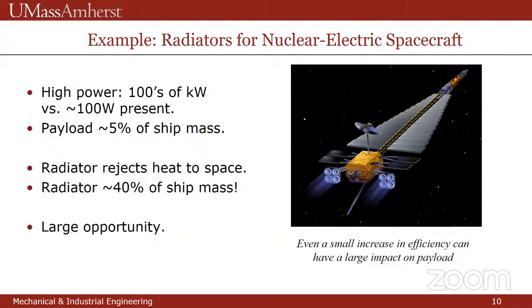On the ground, you build a nuclear reactor next to a river for the cold side of your thermodynamic cycle, but there are no rivers in space. So you end up with this radiator that's about the size of a football field for this little spacecraft. And that radiator is about 40% of the ship mass. And you compare that to a payload of about 5%. So if you can change the mass of the radiator even a little bit, it has an enormous impact on the mission capability.